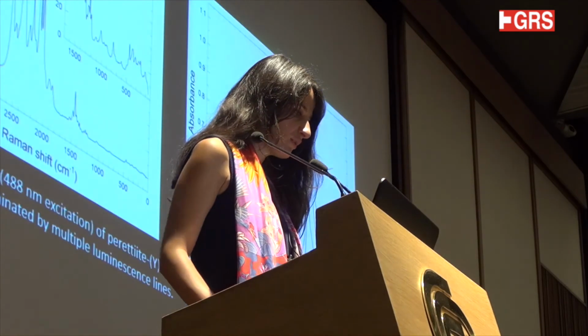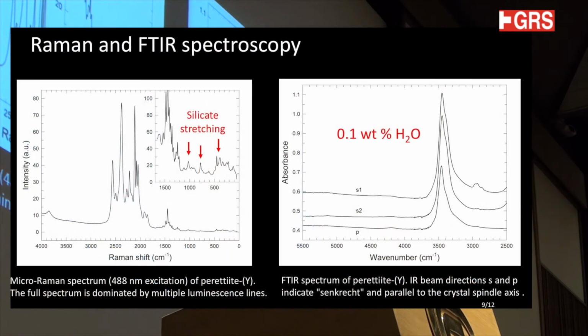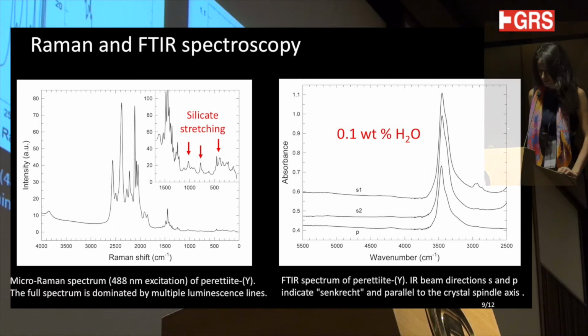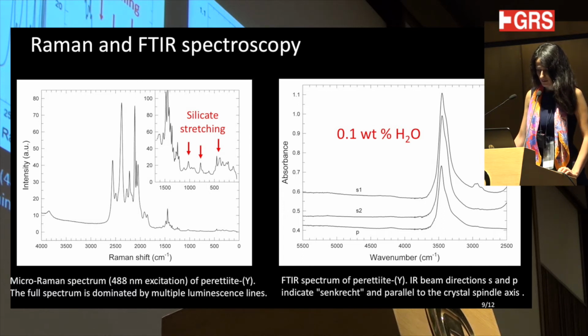We performed also Raman and FTIR spectroscopy. So the Raman spectrum was collected using a micro-Raman system with 488 nanometer excitation line. And we can immediately recognize that we have a problem with the luminescence due to the presence of rare earth elements. And only a long exposure time allowed us to identify some vibrations that are interpreted as silicate stretching, bending, and lattice mode.